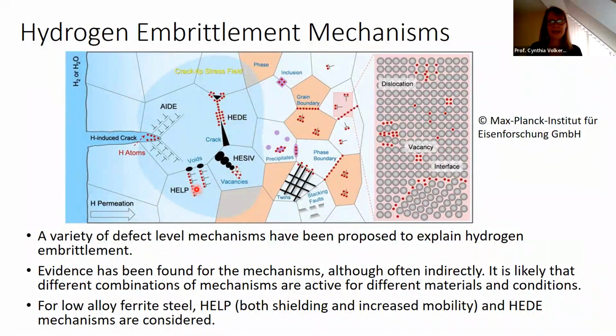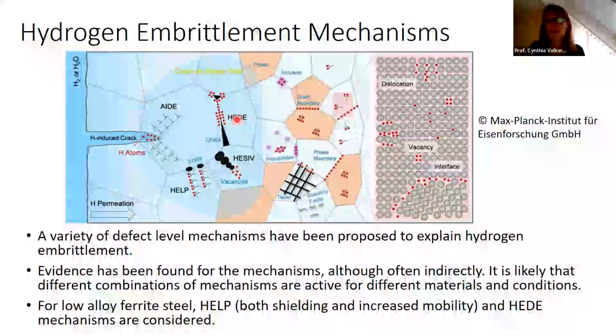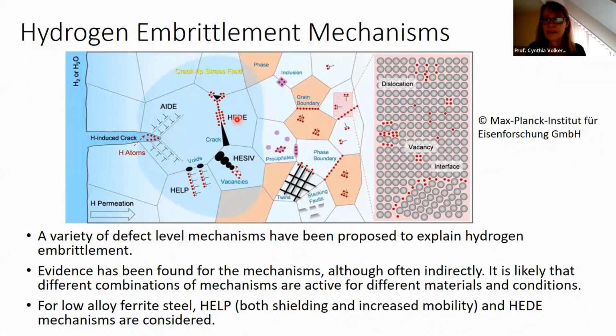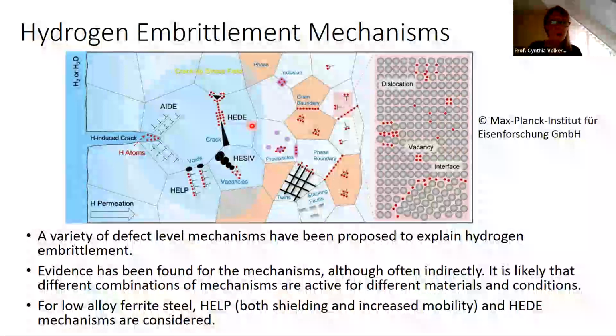For the HELP mechanism, the idea is that the hydrogen enhances the local motion of dislocations. Where there are high stresses and where there is hydrogen, dislocations move more easily. The reason for that enhanced mobility is argued to be either a reduction in the shielding between the dislocations, which interact with each other through their long-range stress fields, or through hydrogen that is segregated to the core, which makes nucleation of kinks and the motion of those dislocations easier. So those are the two ideas for the HELP mechanism. And the HEDE mechanism is one where one argues that the segregation of hydrogen to interfaces lowers their energy and makes simple cleavage along particular crystallographic planes easier. So those are the two mechanisms that are discussed the most here, and we'll see if we can say anything about them during this talk.